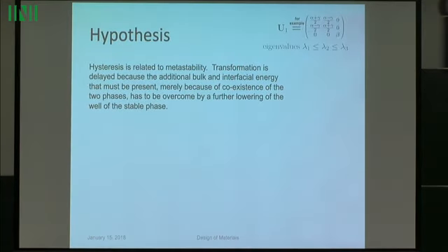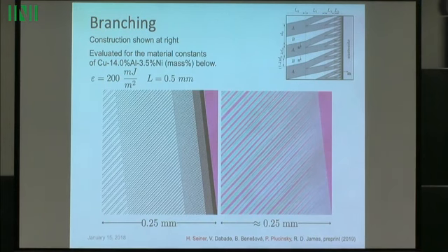Just this calculation. So you imagine that the specimen is all austenite, all red. And now you're at high temperature, and now you're cooling the crystal. You reach a point where the energy well of the martensite is lower. Okay, so it wants to transform to martensite if you're doing energy minimization. But if a little bit of martensite formed in the material, it would also have to accept the interfacial energy, which by either model, the interfacial energy on these bands together with the elastic energy, which are positive sources of energy. So then you would say, okay, that should create an energy barrier. So I should have to lower the temperature more to compensate for the positive sources of energy that are in this picture. Okay?